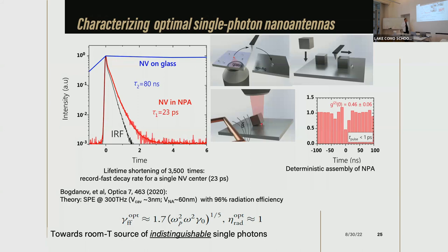Importantly, and those calculations were done by Jacob Khurgin, our collaborator, he showed that if you optimize your system, and in this case it looks like the size of the cavity should be like 3 nanometers, and the size of the cube like 60 nanometers, then the rate with which that system would emit photons would reach 300 terahertz. 300 terahertz would be practically anything that you don't see, even at room temperature, which is particularly attractive. And the efficiency, not surprisingly, is very high. Photons are just outcoupled before even that potentially happens.